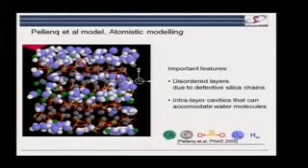They become kind of rough. And this is why you don't see a good X-ray diffraction pattern. Also, because of these defects, we can actually have water molecules between these layers. This becomes very important as regards the interaction of water with CSH.